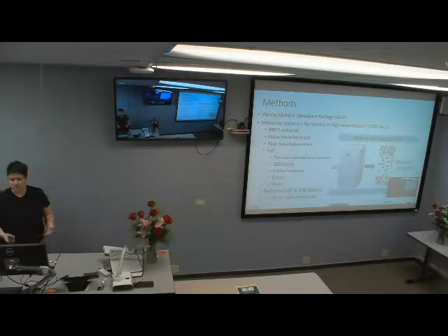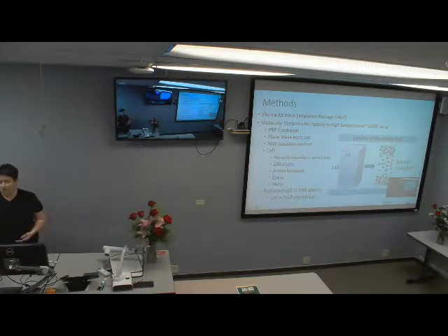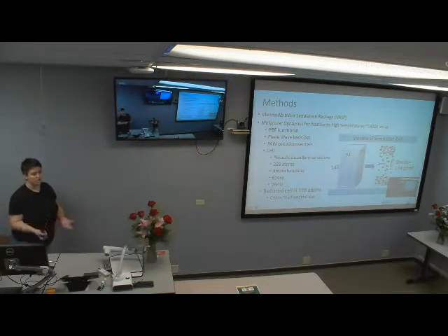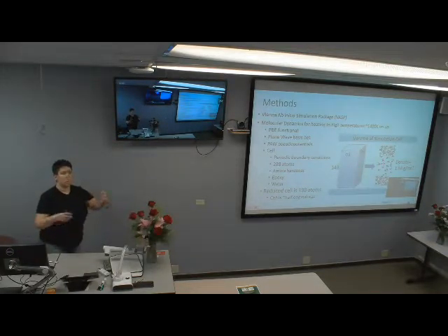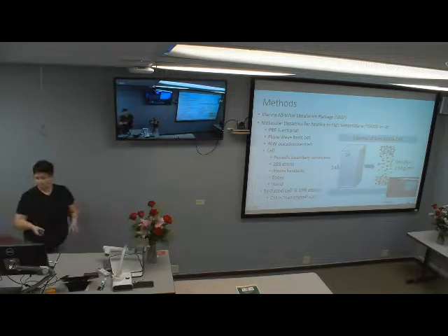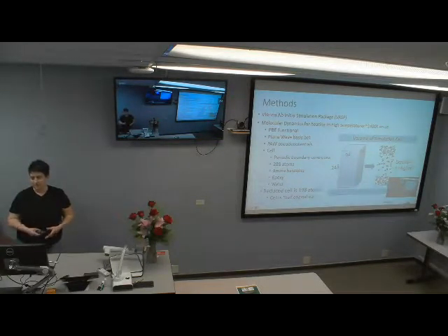So we used a Vienna ab initio simulation package, and we did the molecular dynamics with the heating. And the goal of the high temperatures was, well, we know that if we use real life temperatures, that's great, we can figure out that our system will work. But if we heat it up and see if it still stays together, it'll be interesting to see, you know, we know in real life it wouldn't exist necessarily because it's going to degrade, but maybe it'd be interesting to look at the physical interactions or what happens. We used a PBE functional plane wave basis at pseudopotentials.